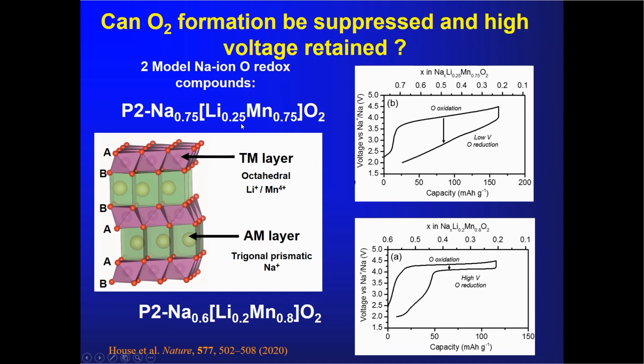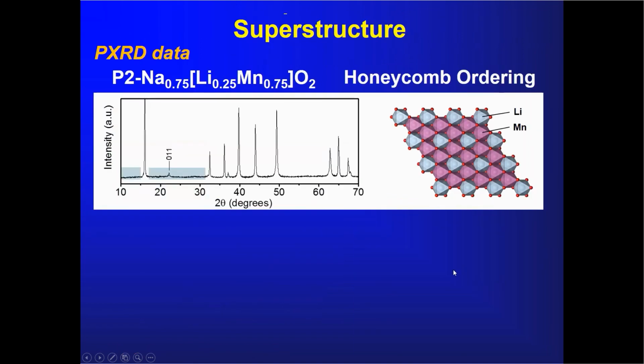Here we have 0.25 lithiums on the transition metal site. Here we have only 0.2. So very similar compositions, same crystal structure, really very different electrochemistry. One shows voltage hysteresis, the so-called 0.25 compound, and one, for a large part of its electrochemical curve on the first cycle, doesn't. This is what we would really like to have in our compound, coming back along more or less the same pathway on discharge as charge. So understanding these compounds will be helpful in thinking about mitigation of molecular oxygen formation.